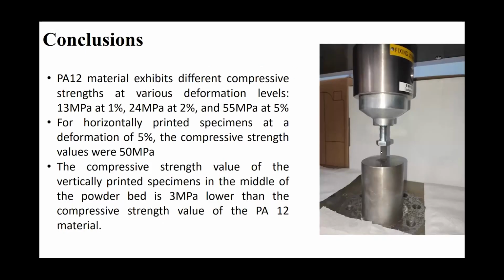In conclusion, PA12 material exhibits different compressive strengths at various deformation levels: 13 megapascals at 1% displacement, 24 megapascals at 2%, and 55 megapascals at 5%. For horizontally printed specimens at the deformation of 5%, the compressive strength values were 50 megapascals, and the compressive strength value of the vertically printed specimens in the middle of the powder bed is 3 megapascals lower than the compressive strength value of the PA12 material.